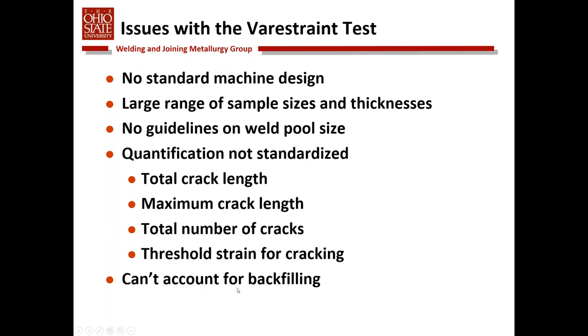The other thing with the Varestraint test is it can't account for a phenomenon called backfilling, where liquid films along grain boundaries can actually come in and backfill and repair cracks. There are alloy systems out there that are designed to do that, and the Varestraint test does not do a very good job of predicting their weldability.